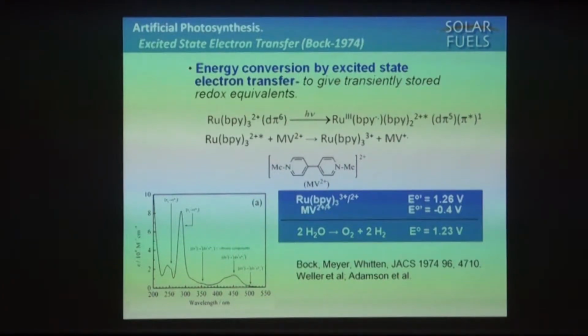And that gives it an excited state, a so-called metal to ligand charge transfer state. If you look at the electronic description, the photon drives an electron from an orbital that's mainly on the metal to one that's mainly on the ligand. Therefore, metal to ligand charge transfer. The excited state lasts a microsecond in solution. If in the solution you add a couple millimolar of an electron acceptor, in this case methyl viologen, so it's just a 4,4'-bipyridine methylated twice, electron transfer quenching of the excited state occurs to give the oxidized form of the complex and the reduced form of methyl viologen.